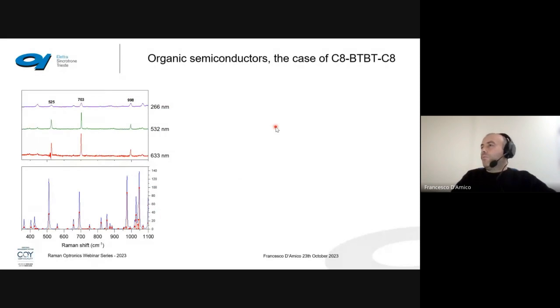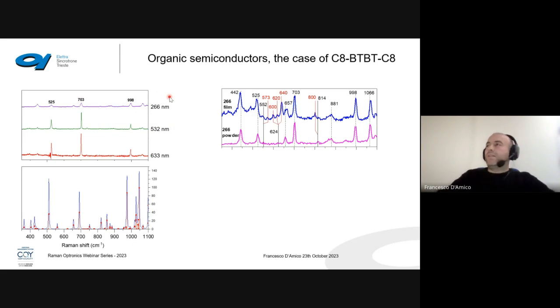But if we go to lower wave numbers, these are simulations that we have done to understand which kind of vibration we are analyzing. We see that this peak decreases in intensity, passing from the visible to the ultraviolet. And in particular, at these two excitation wavelengths we cannot investigate surfaces, because basically we can study the powder, but the film appears with strong fluorescence. At 266 we can, and we see differences in the spectra between film and powder, not in all the normal modes, but only near specific normal modes that are modified in position.